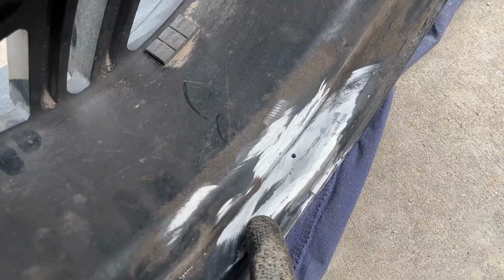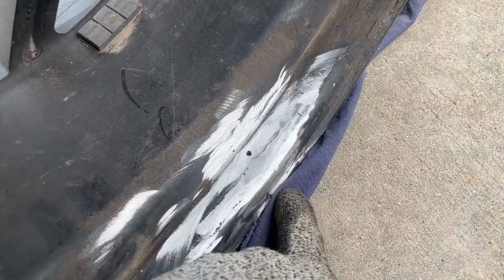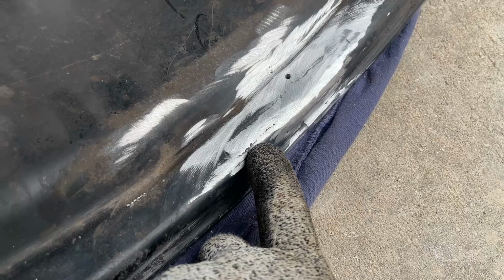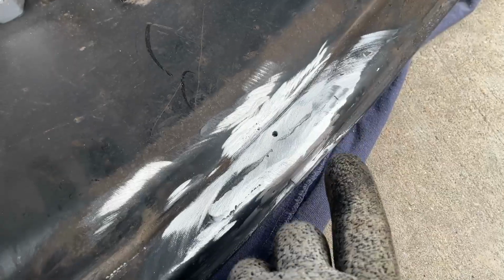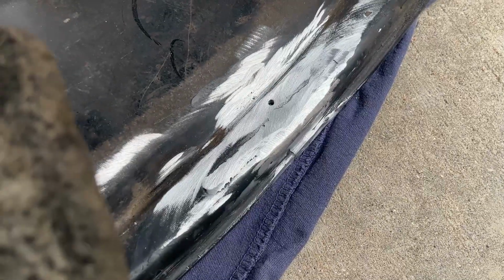What I'm seeing along in here, this is the original weld that they welded transverse to the crack, right, at 90 degrees across there. I was trying to get into that just a little bit. That's actually the toe of the weld, even though it looks like a crack. That's where it didn't really blend in with the base metal. I was looking to see if this weld had cracked, right, and maybe that's why they chased it, or did they think that by welding across it, it would stop the crack? Well, that's not the case. We've got to eat the crack out, put new weld metal in here, and then we don't need to weld across there, right? That's not going to do anything for us. So unless I find something more when I'm opening up this can of worms, I think we're going down the right path. We just need a new flapper disc for aluminum.